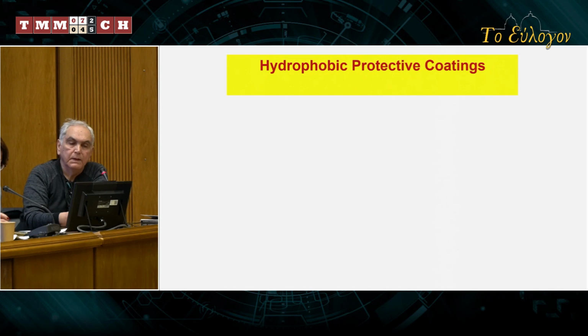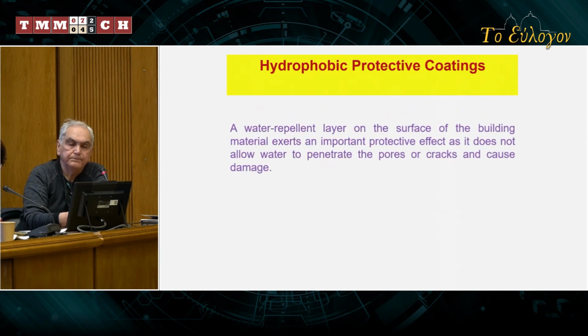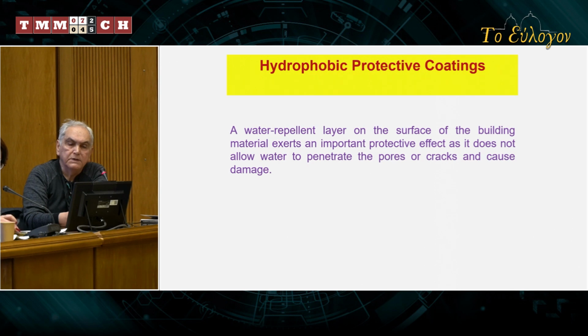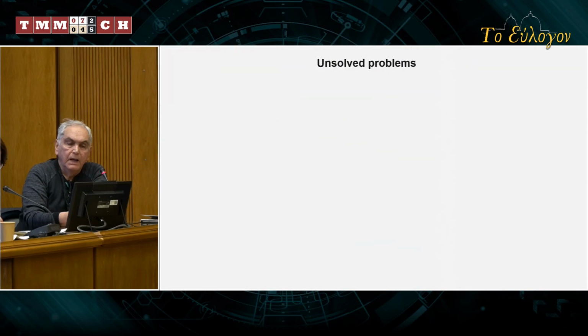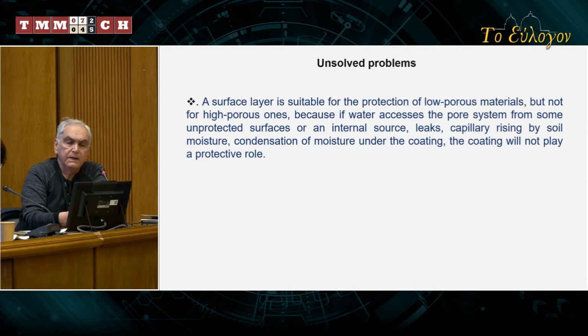Second method, hydrophobic protective coatings. A water repellent layer on the surface of the building material exerts an important protective effect, as it does not allow water to penetrate the pores or cracks and cause damage. Unsolved problem: a surface layer is suitable for the protection of low porous material but not for highly porous ones, because if water accesses the pore system from some unprotected surface, or an internal source such as leaks or capillarity from soil moisture, condensation of moisture under the coating will not play a protective role.